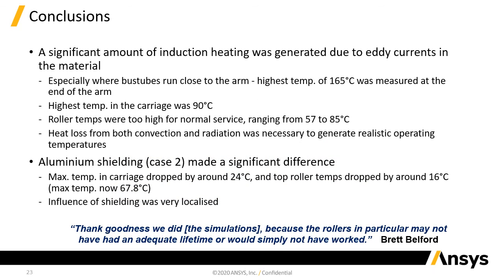So just to conclude, as we saw, the original design had quite a high resultant temperature from the induction heating, 165 degrees, and the carriage area was about 90 degrees. And this obviously meant that the roller temperatures were far too high for normal operating, being up to about 85 degrees or so. And so we did need to find a way to mitigate the heating from these cases. And this is where we brought in the aluminium shielding, which made quite a significant difference to the temperature in the carriage area. But obviously the shielding was very localized, and moving outside of that, we still ended up with the same temperatures as before.